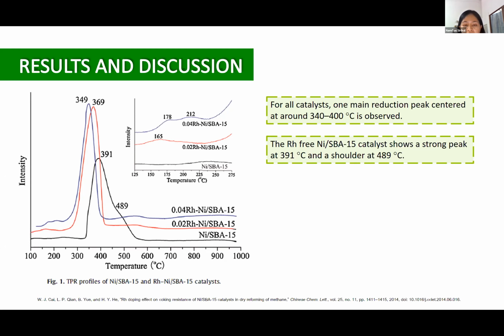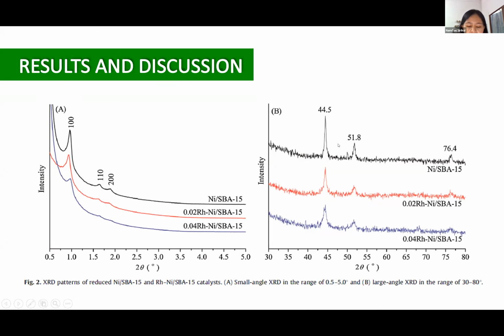Figure 2A is the small angle XRD pattern of the catalyst. There are three resolved peaks of SBA-15, indexed as reflections associated with hexagonal symmetry. In the large angle XRD pattern in figure 2B, the reduced nickel on SBA-15 and rhodium nickel on SBA-15 samples show the reflection assigned to nickel fcc with a lattice constant of 3.523 angstrom. No peak associated with rhodium was observed, suggesting that rhodium is well dispersed or the content of rhodium is too low to be detected by XRD.